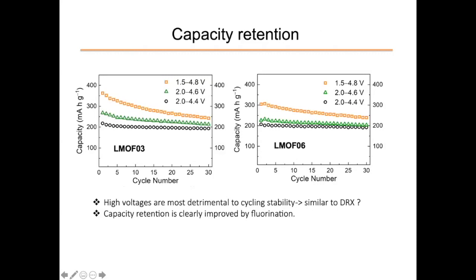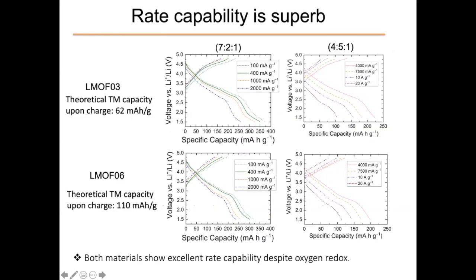Capacity retention is good, but degrades when you go to a higher voltage cutoff, and I'll come to that issue. It turns out that this is mostly an electrolyte issue, not a materials issue. And capacity retention also improves with higher fluorination.